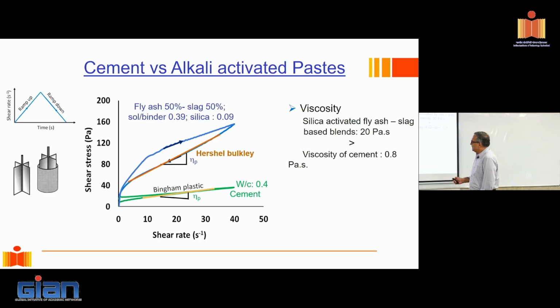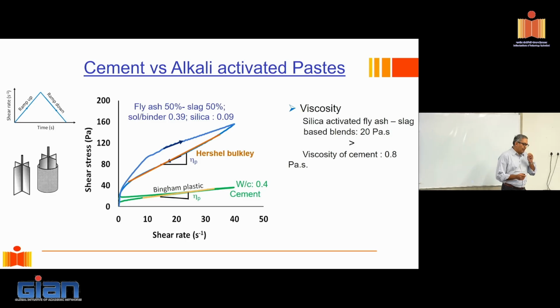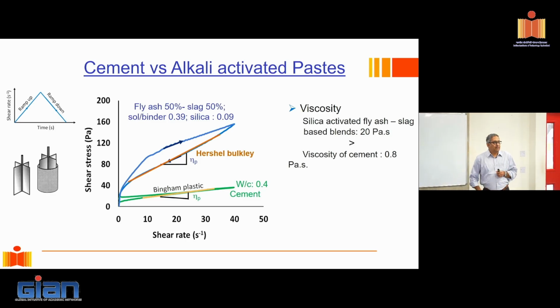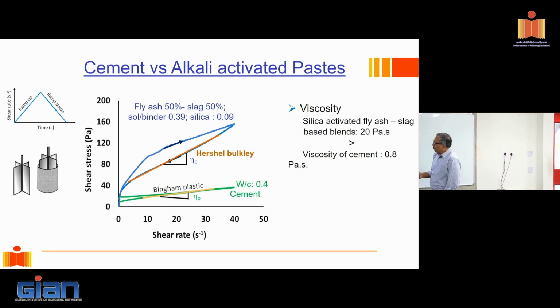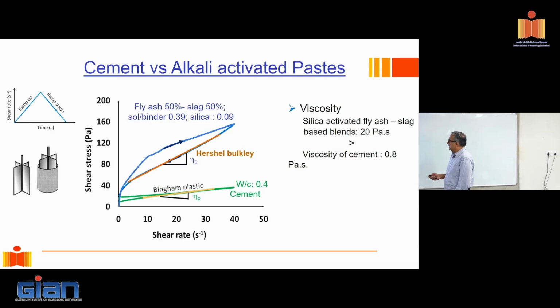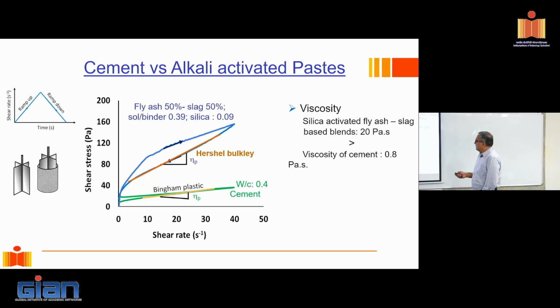It's a fine point to note here that most alkali activated materials have what we call a Herschel-Bulkley type of behavior. And what is more important is we identify the slope of this line with plastic viscosity. We've already seen this in the last lecture. On average, if you look at the slope here, which is for cement paste, and the slope here, and mind you, these two have almost similar solids concentration. How do I identify the solids concentration? Well, here the water to cement ratio is 0.4. Here the solution to binder is 0.39. So they're almost comparable, right?